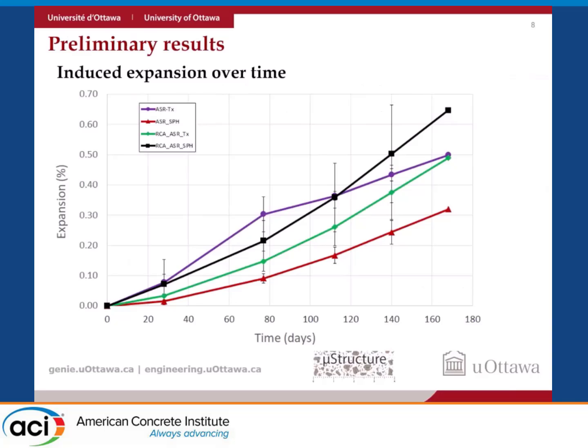Good. So talking about results, and starting with conventional concrete, it's interesting to know that the expansion over time can be huge, right? First of all, as expected, the Texas sand is almost a bomb, and we would have deterioration over time. Springhill is a coarse aggregate, very reactive as well. This is, by the way, a Canadian aggregate, the one that has been used to build Mactaquac Dam. And we can see that there is very important deterioration and expansion over time as well.